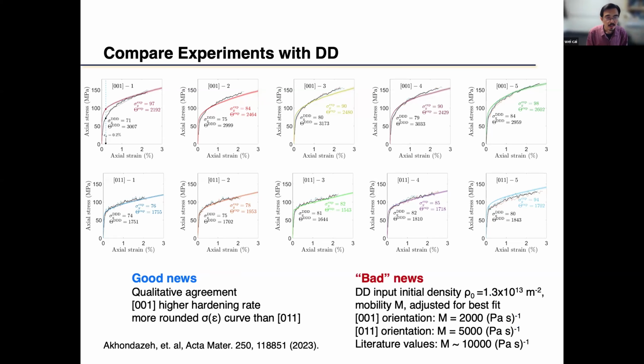But at the same time, this is not a fully first principles prediction, okay? The discrete dislocation dynamics simulation is not a first principles model. It has a lot of inputs, and the result depends on those inputs. And what I'm showing here in this work, these curves are the inputs that agree with the experiments the best. If you change those inputs, the results will be different. So you can say that the parameters have been adjusted in the DD to match the experiments. But the fact that they actually can match, I think is encouraging.